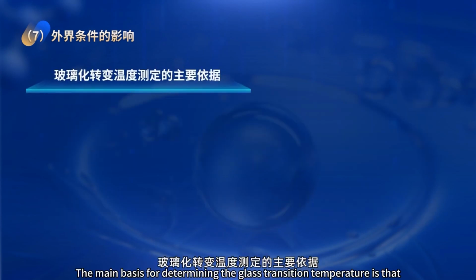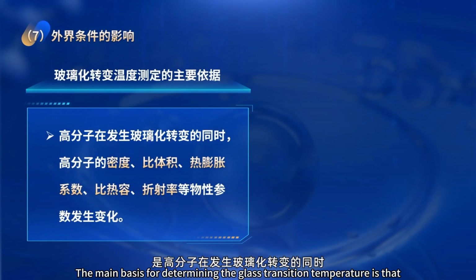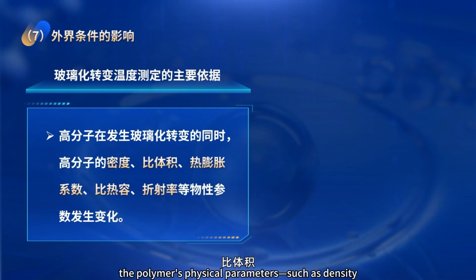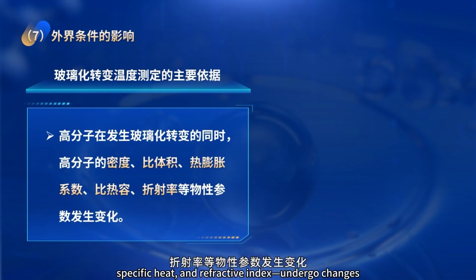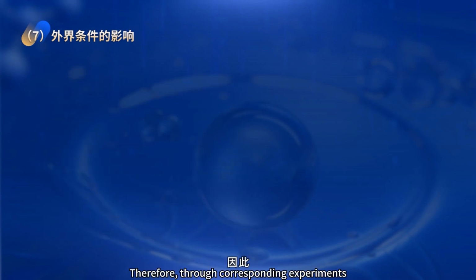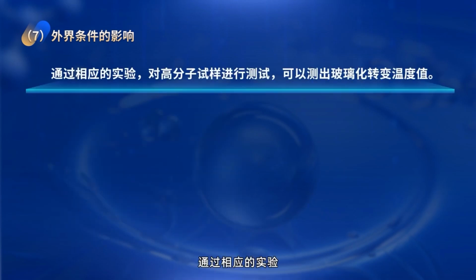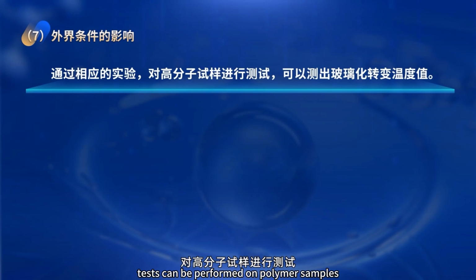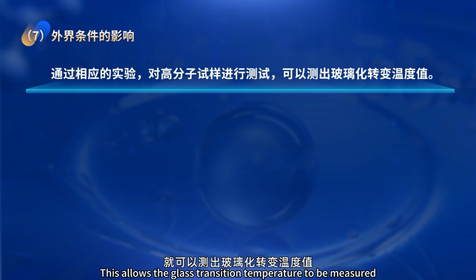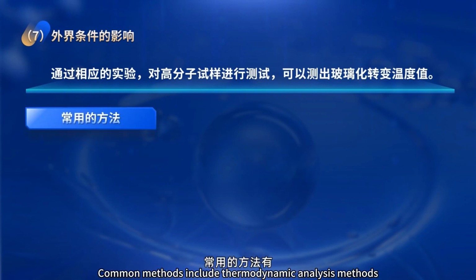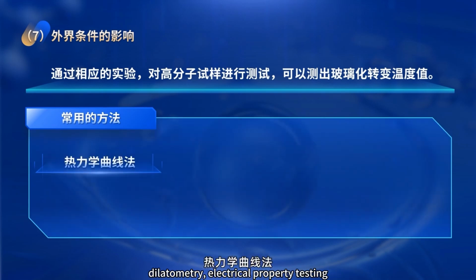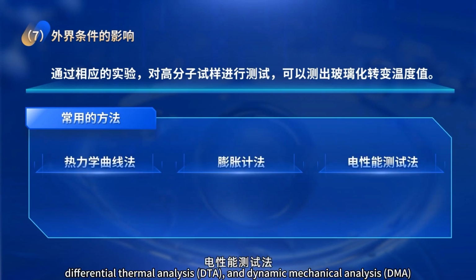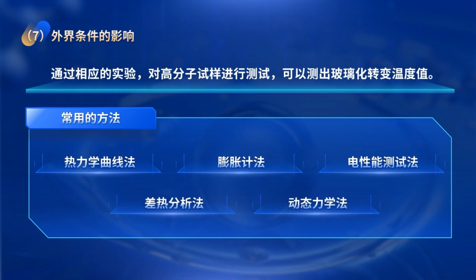The main basis for determining the glass transition temperature is that, when a polymer undergoes the glass transition, the polymer's physical parameters, such as density, specific volume, coefficient of thermal expansion, specific heat, and refractive index, undergo changes. Therefore, through corresponding experiments, tests can be performed on polymer samples. This allows the glass transition temperature to be measured. Common methods include thermodynamic analysis methods, dilatometry, electrical property testing, differential thermal analysis (DTA), and dynamic mechanical analysis (DMA).